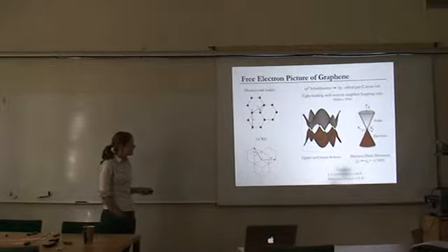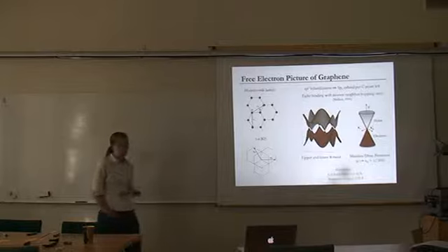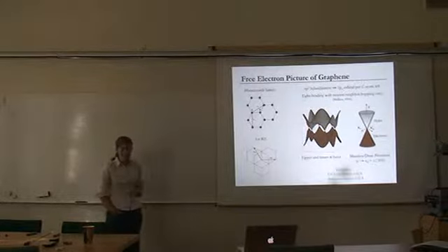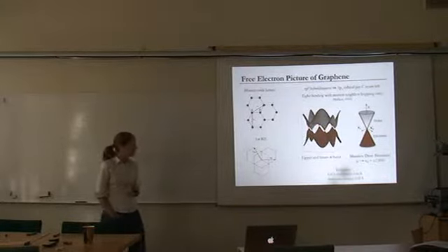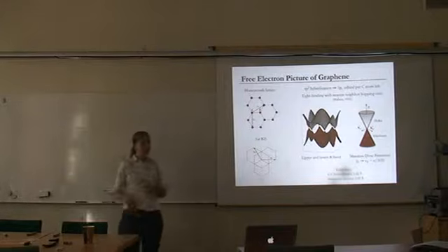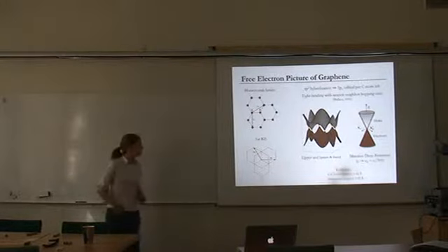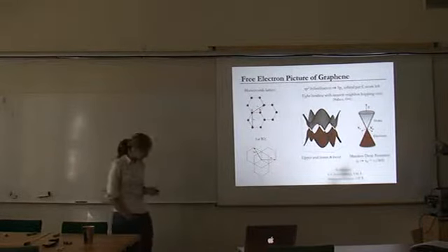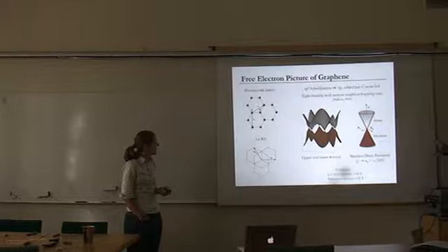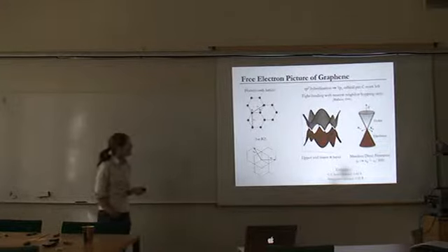For graphite, you can just keep this number in mind. The CC bond distance is around 1.42 angstroms, so that's the distance here in plane, but the interplanar distance is more than 3 angstroms. So to a first approximation, you can think of graphite as essentially almost independent layers of graphene. Okay, so that was a crash course in graphene. You've probably already seen this.